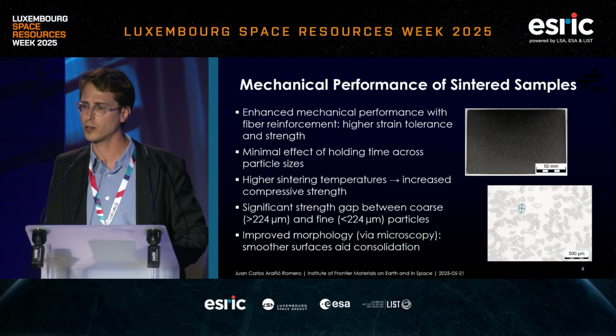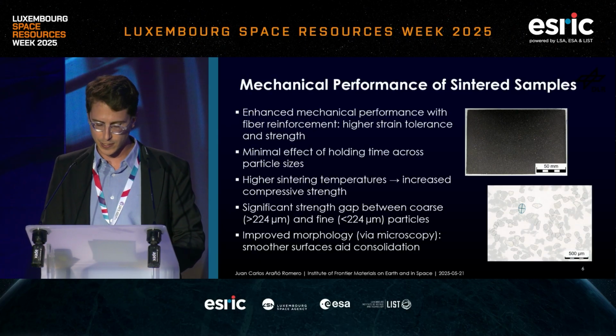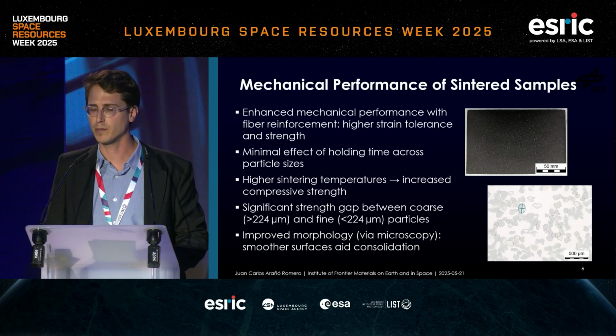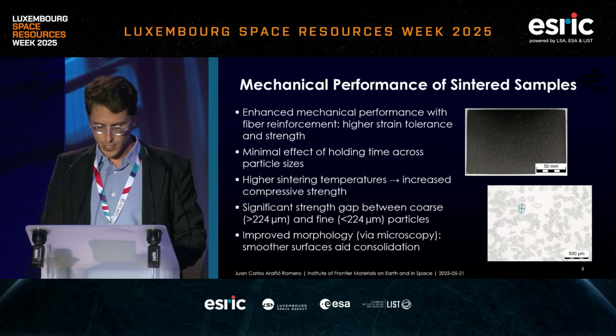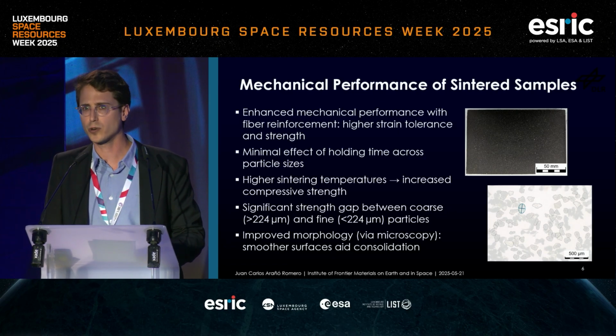In the top picture, you can see one of the tiles that we produced, with a homogeneous and quite flat surface. And at the bottom, one of the pictures that we used during the microscopy analysis. These results make us look more closely at what happened to the material during the sintering, which leads us to the thermal behavior.